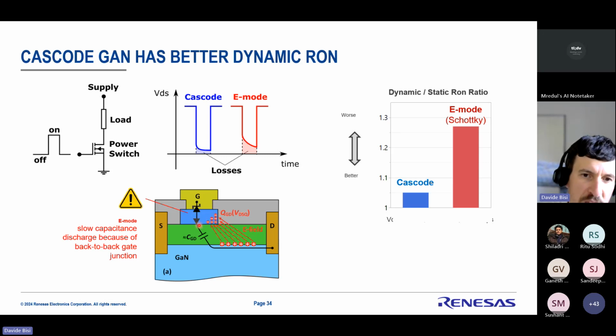What that means is that when you're switching the device from off to on, there is residual charge trapped in between these two junctions. The residual charge is negatively ionized, and so that is debiasing the channel. What that gives you is dynamic Rdson. The device does not turn on fully because you have trapped charge between these two junctions. If you look at the data, if you measure the dynamic Rdson of a Schottky E-mode, it is almost 30% higher than the static. Whereas if you do the same measurement on a cascode or even an E-mode with an ohmic contact, the resistance is much better. So this is a challenge. I know they are making progress on this, but this has been one of the key challenges for E-mode.